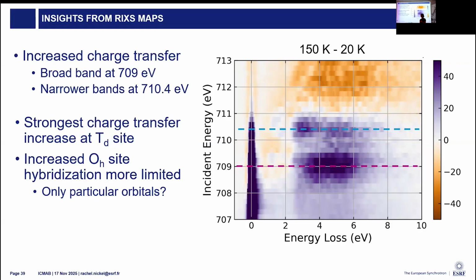And what about the surfaces? I mean, they might be very different, no? Yes, so RIXS is bulk sensitive. Unlike XAS, where it's usually electron yield measurements and we're very sensitive to the surface, RIXS is a bulk probe, an inefficient bulk probe, but bulk. Okay. Thanks. Going between nanoparticles and films, we're going to have differences in strain as well, which could factor in.